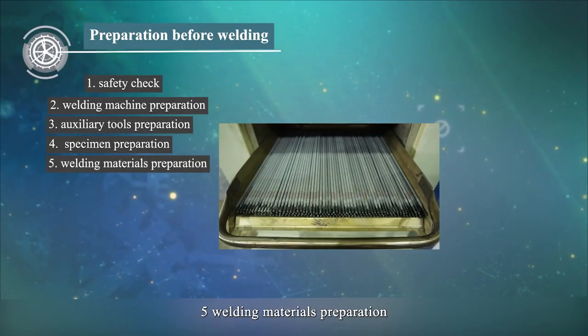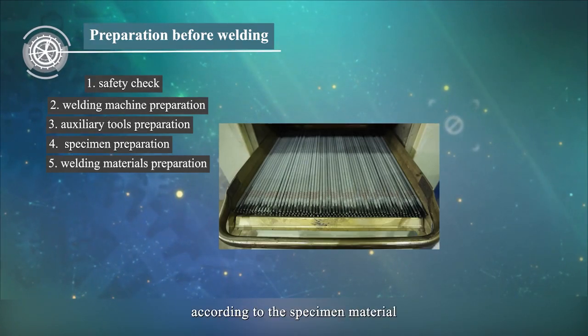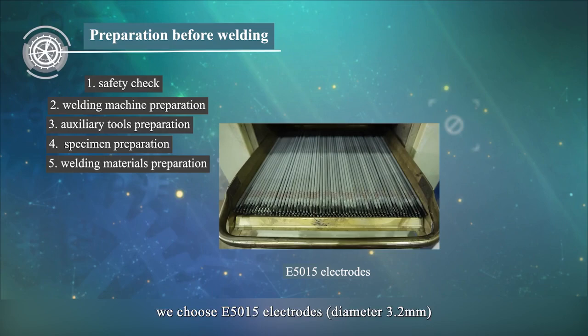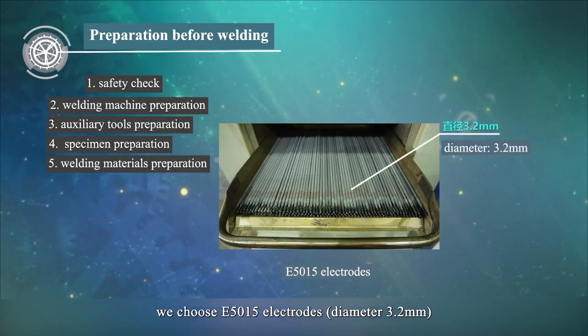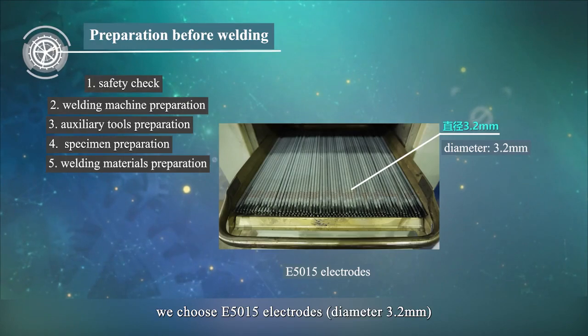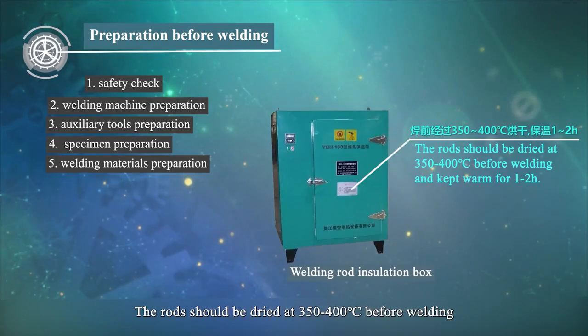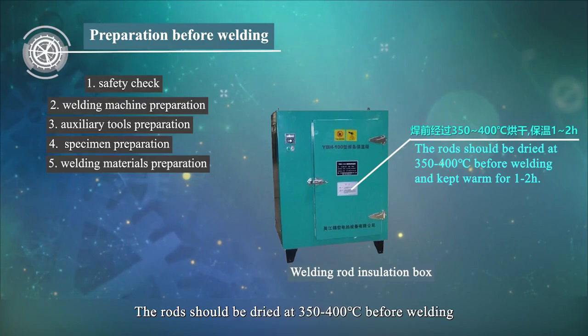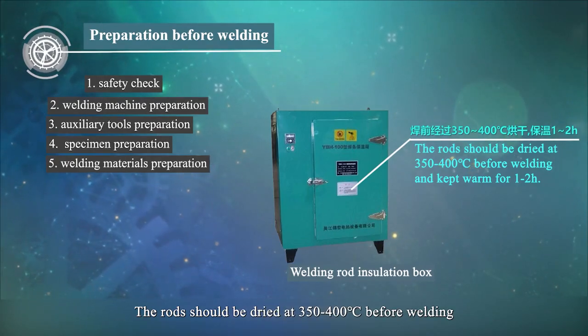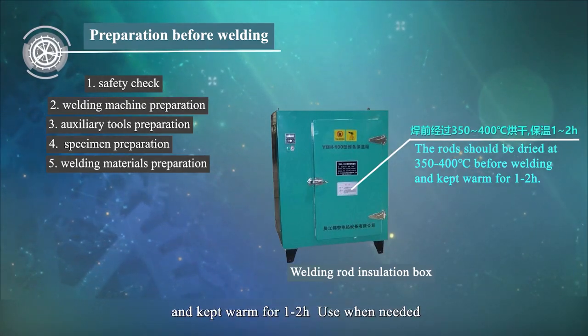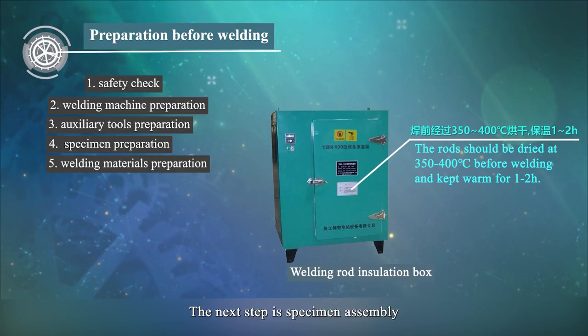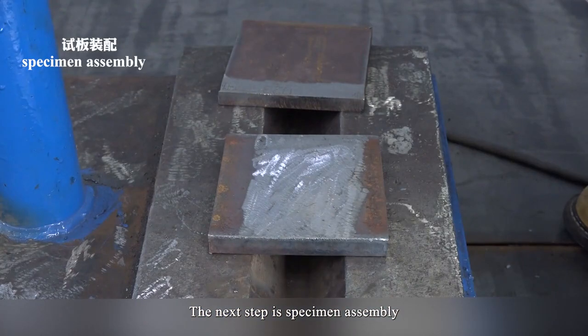Fifth, welding materials preparation. According to the specimen material, we choose E5015 electrodes, diameter 3.2 mm, as they have better processing properties. The rods should be dried at 350 to 400 degrees before welding and kept warm for 1 to 2 hours. Use when needed. The next step is specimen assembly.